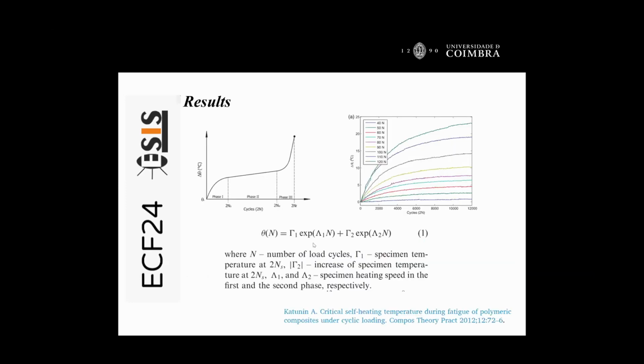Okay, about the results. Here the strategy, nothing is new. We have here the typical response of the material to the applied load, where you can observe that the temperature increases in three regimes. Phase 1, Phase 2, and Phase 3, which is characterized by an initial, higher increase of the temperature. After that, there is stabilization and again a strong increase of the temperature and final collapse. This is very well reported in the literature, and we can see the diagram.